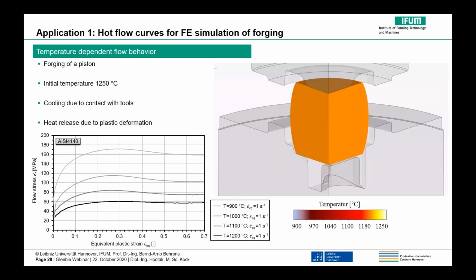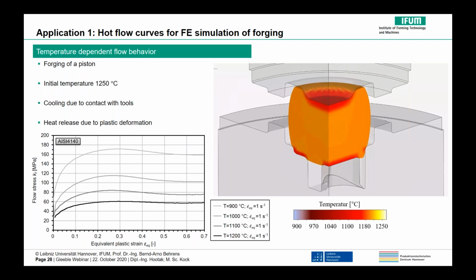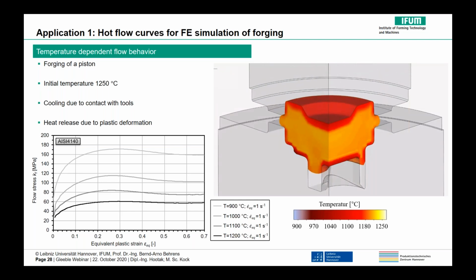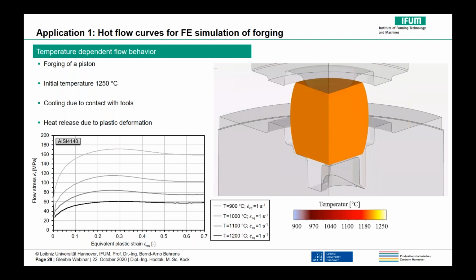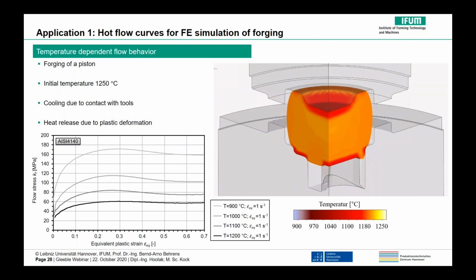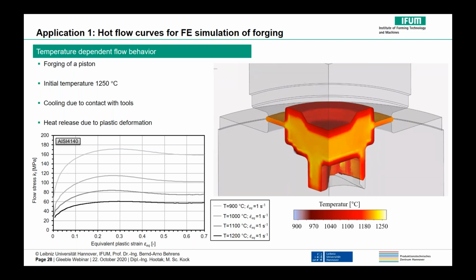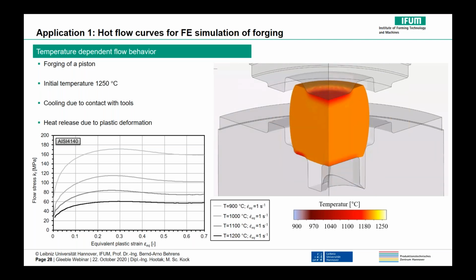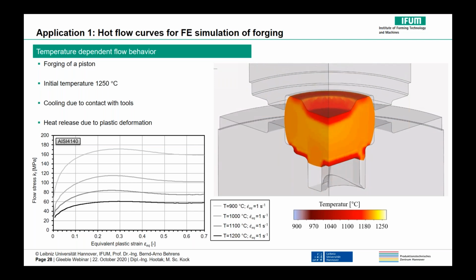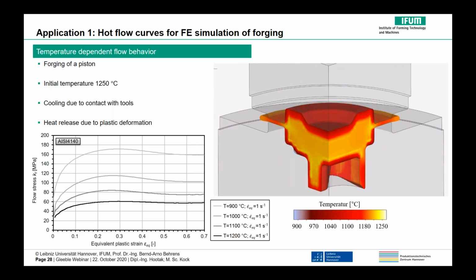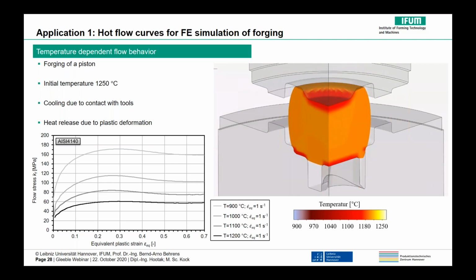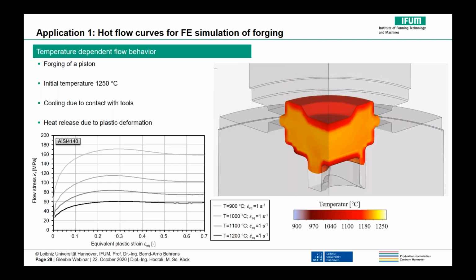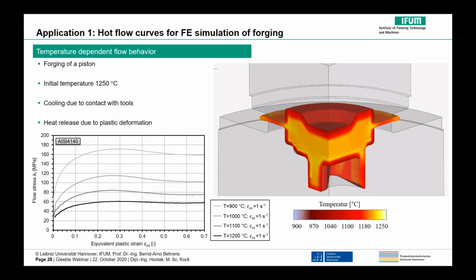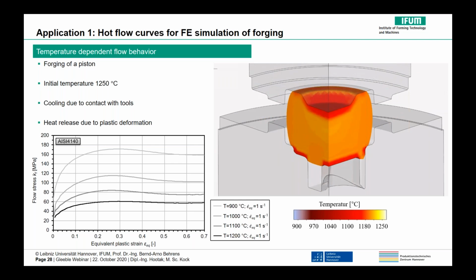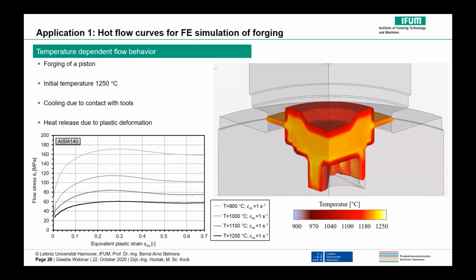On this slide, we now see the temperature development of the workpiece material during the forming process. We notice that during the forming process, which takes place in less than 1 second, a significant temperature gradient is established in the material. At the surface of the material, there is a temperature of about 900 degrees Celsius at the end of the forming process, while inside the component, there are still high temperatures up to 1200 degrees Celsius. As is typical for forging processes, the tools were modeled in the simulation at a temperature of about 250 degrees Celsius. This explains a significant cooling of the material by the tool workpiece contact.